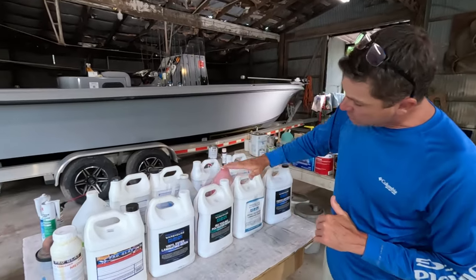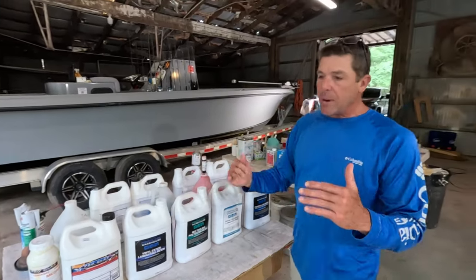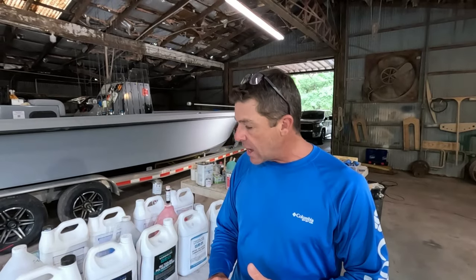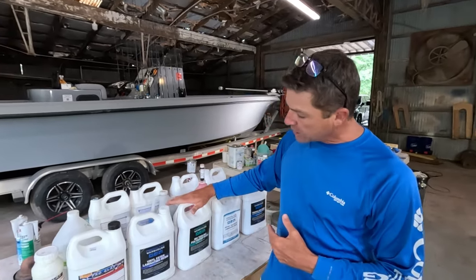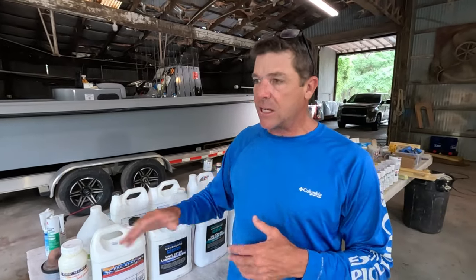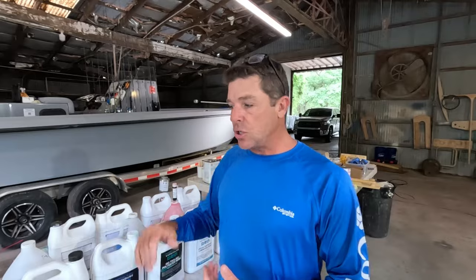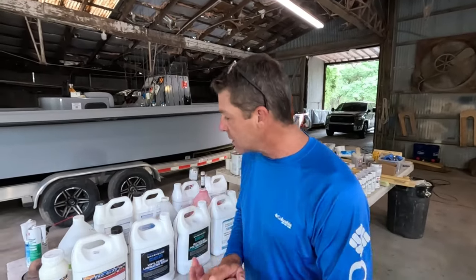All of the polyesters and vinyl esters are compatible with one another. You can put epoxy over the top of vinyl esters and polyesters, but not vice versa. So if you've got a fiberglass hull boat and you want to put an epoxy barrier coat on it, that's totally fine. Or if you've done repair with a polyester or vinyl ester and you want to use epoxy to seal it. But if you use an epoxy putty for the repair, you don't want to put polyester resins or gel coats back over the top of that.